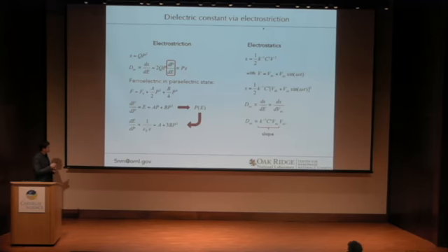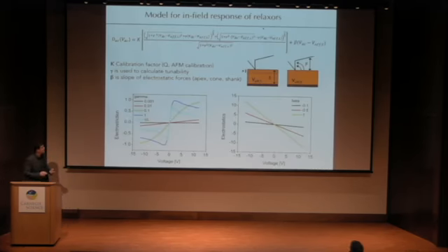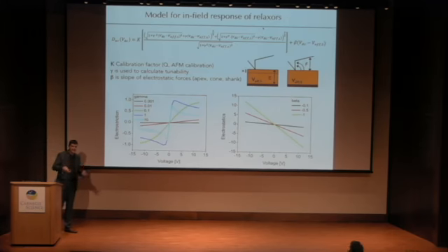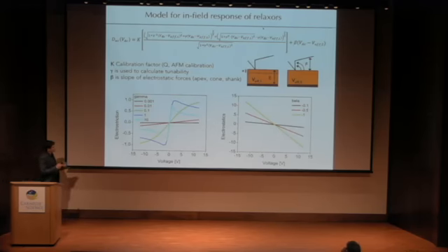Then Sasha suggested, well, let's throw in a very simple expansion for what the dielectric constant is going to look like as a function of polarization, take the derivatives of it, invert it, and build a simple model for what you would expect for the vibration of the tip that's excited in the presence of the polarizable material. This is not a very pretty looking expression, but it has several parameters to which we can directly fit the data, such as gamma, k, and beta.